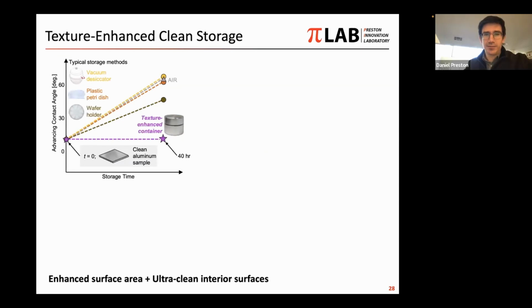In our case, we said, well, if it's going to cover the surface, maybe what we can do is build a texture enhanced storage vessel such that the walls of this container in which you store your sample actually try to pull away most of the contaminants such that they don't stick to the sample, and it remains clean. We did this by enhancing the surface area of the container walls and also making sure that those walls with the enhanced area were ultra clean at the point at which you store the sample. And then basically the container is sacrificial. It pulls all the contaminants such that the sample remains clean.